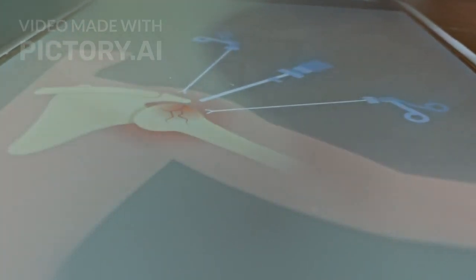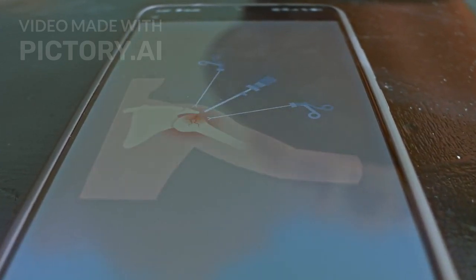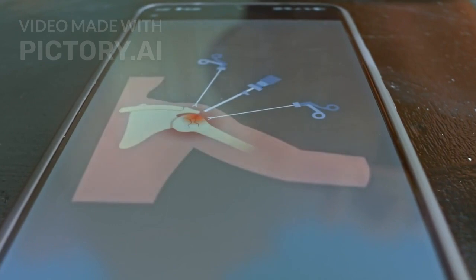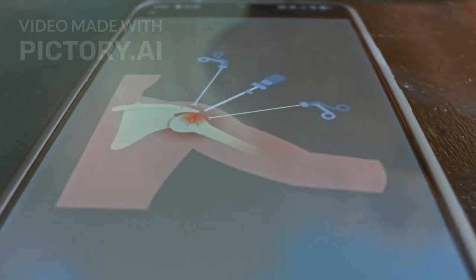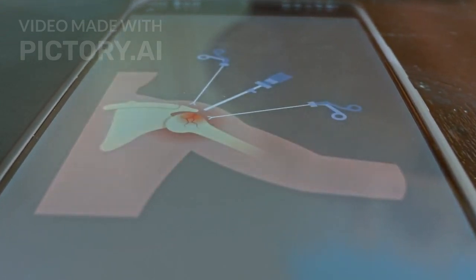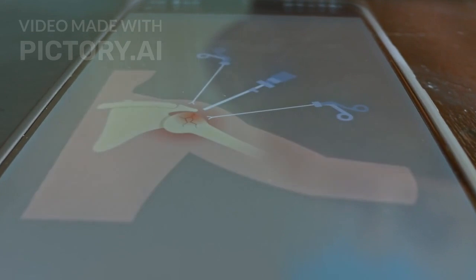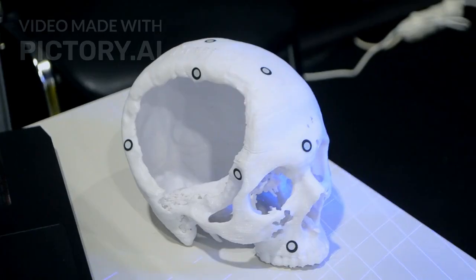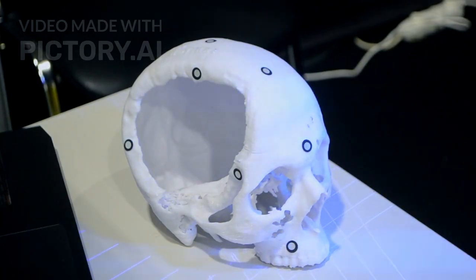Okay, one more approach mentioned. Making powder parts with internal channels, using solvent jetting for the mold again, but this time with spark plasma sintering. SPS. How is this one different? This one's really focused on creating those complex internal channels, like the blood vessel networks in bone scaffolds. Ah, okay. So you use solvent jetting again, but this time you print the mold out of graphite. The mold is the negative space of the channels you want inside the final part. A graphite mold defining the internal voids.